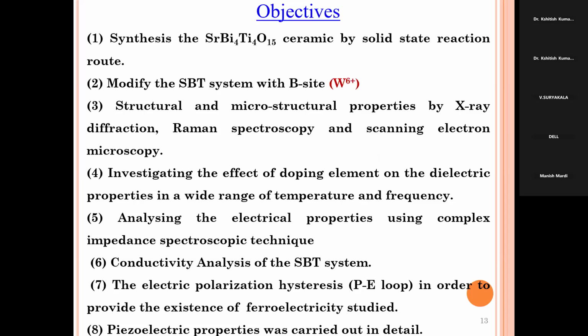A side means strontium. Instead of strontium, we have doped barium and calcium. On the bismuth side, as bismuth is 3+, we have changed it to lanthanum and gadolinium. And on the titanium side, we have substituted niobium and tungsten. Here I have shown only the good property that I got when tungsten was placed on the titanium side. Titanium is 4+, but tungsten is 6+. Whenever we substitute tungsten on the titanium side, the material gives better properties compared to pure SBT.